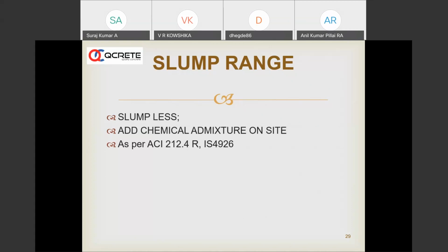Generally it will be about half a liter or 1 liter of admixture diluted in about 5 liters of water, because if you don't dilute it, the admixture cannot be spread uniformly in the entire body of concrete. So you take a little amount of admixture, about half a liter or 1 liter, dilute it in about 5 to 10 liters, and mix it thoroughly before you unload to boost the slump. This is a very well accepted method if the slump is less.